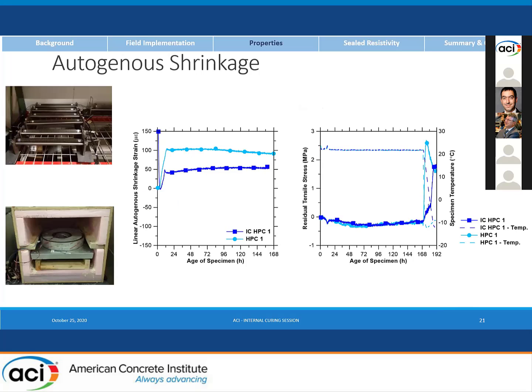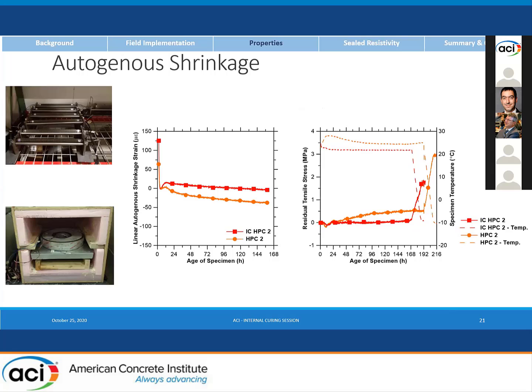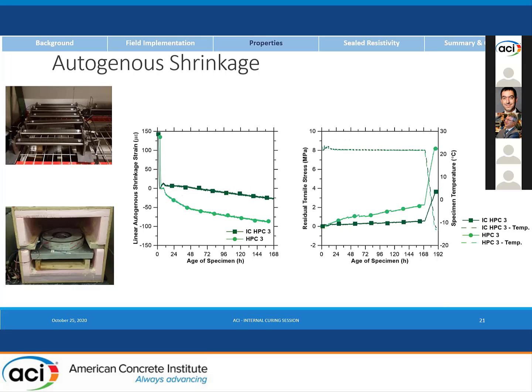Looking at the autogenous shrinkage, I've got linear autogenous shrinkage on the left, the dual ring test on the right, so restrained autogenous shrinkage. I'll skip over the first one because it was actually an expansive cement. I'll skip over the second one because we did have a testing error on the right with the temperature, so it's not as obvious to see what's going on. And so I'll stop on this one, and you'll see that indeed we have a reduction in the residual tensile stress built up due to the restraint of that shrinkage.